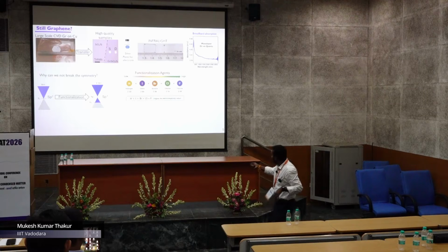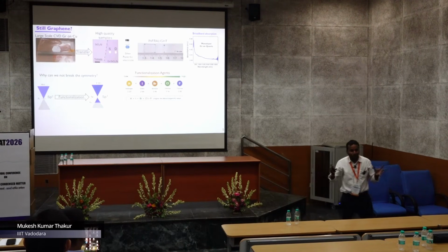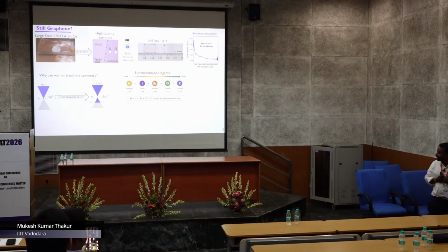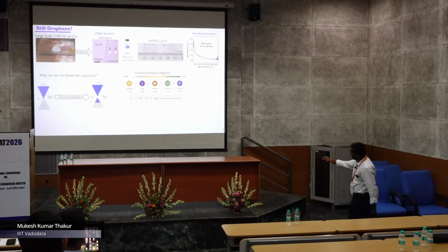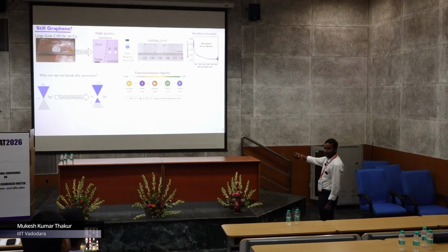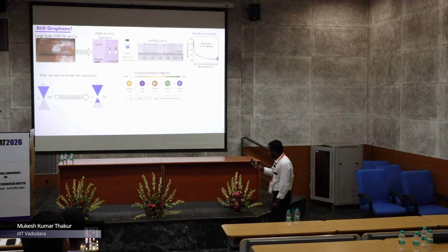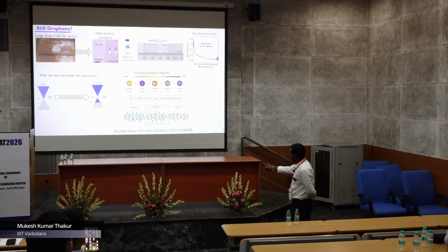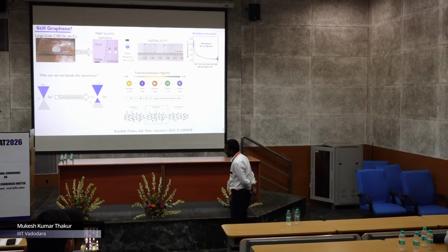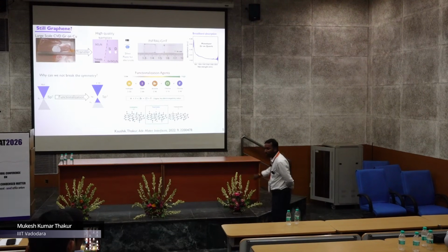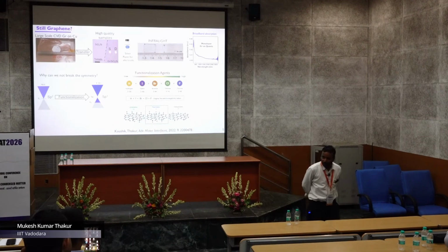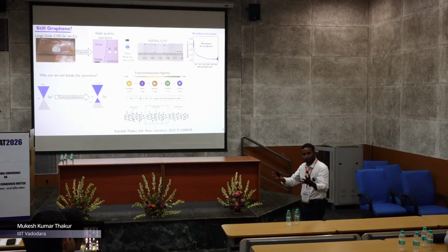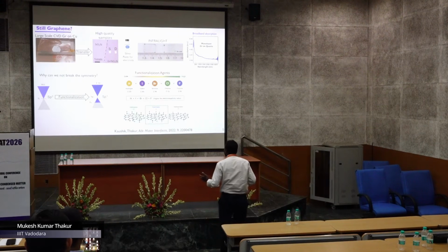The good thing with graphene is that it has delocalized pi electrons, lots of pi electrons, and other atoms love electrons. They will easily take the electrons from graphene. If you see the electronegativity, fluorine is very high, so they love electrons more. So we tried to functionalize this with different functional groups: chlorine, fluorine, hydrogenation. We tried all, and we see fluorine works nicely because it has very high electronegativity, and it will go and make a carbon-fluorine bond.